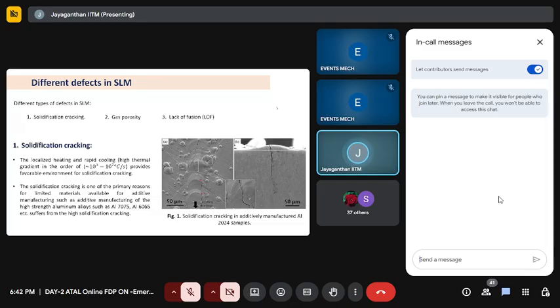And when it goes through the casting route, there is always solidification cracking, even if you go through 3D printing also. The first problem is solidification cracking. Second one, gas porosity. Third one is lack of fusion. Okay, the solidification cracking, why does it occur? The reason being the localized heating and rapid cooling. Typical cooling rate is of the order of 10^3 to 10^6 K per second. Obviously, they provide a favorable environment for solidification cracking.